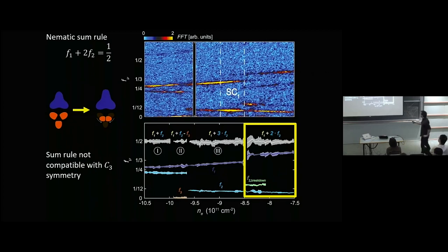Okay, and you can see that because there's this funny behavior of the quantum oscillations, where one of the quantum oscillations corresponding to this big Fermi surface grows by exactly the area of one of the small Fermi surfaces. And when that happens, you see that the small Fermi surface doesn't change size, but you start to see a breakdown feature. It looks like those Fermi surfaces have depinned from the corners of this triangle and have come close to each other. And you can tell this is a quantum oscillation coming from magnetic breakdown because it scales with magnetic field differently. So it looks like there's a nematic transition.